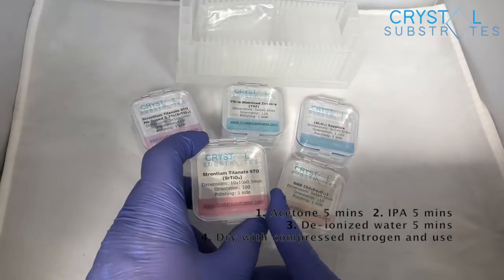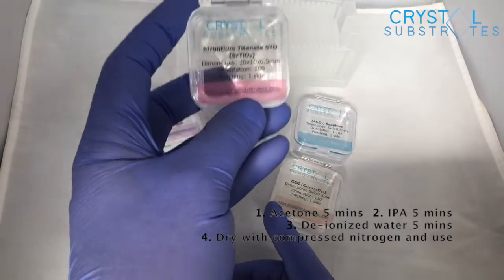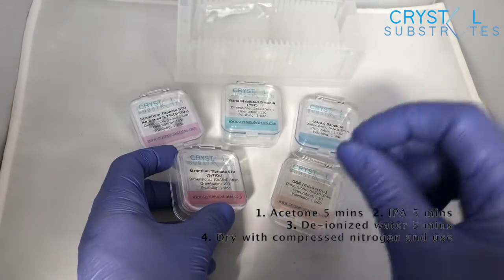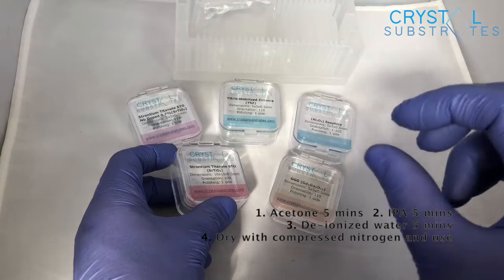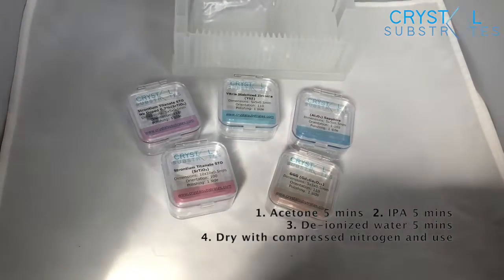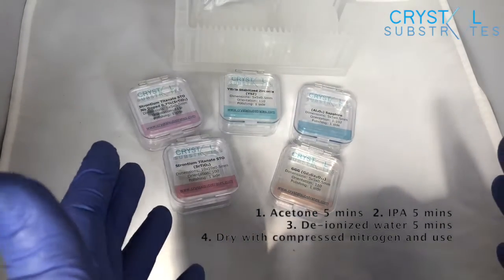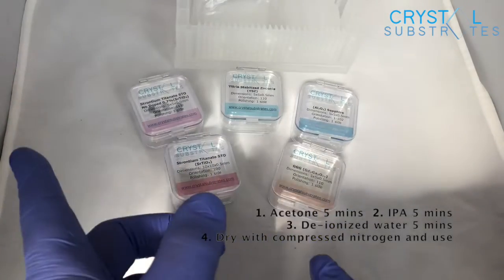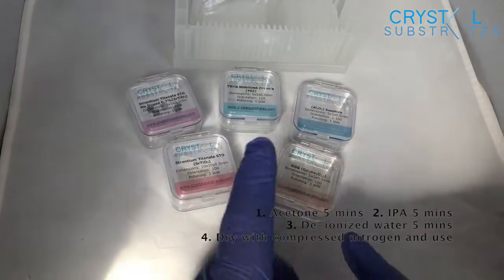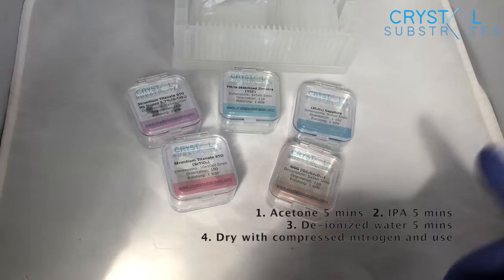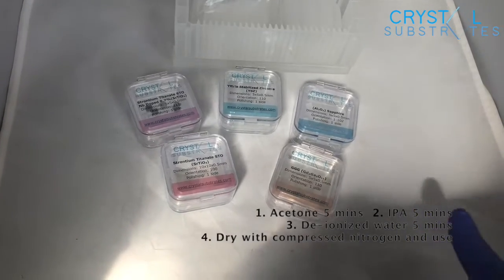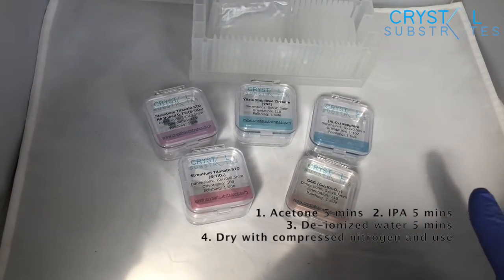But acetone will also do the same, so you can put them in a small beaker with a small amount of acetone so they're fully covered, put them in an ultrasonic bath for 3 to 5 minutes, and then you take it out. You go from acetone, then IPA, and then from IPA into DI, so 3 to 5 minutes in IPA, then 3 to 5 minutes in DI.